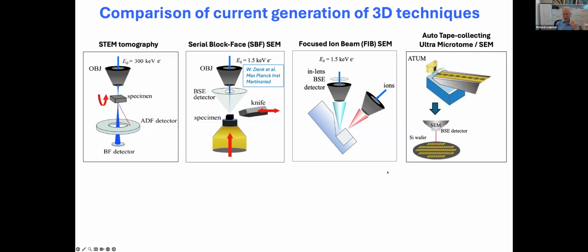And then at Harvard, there's this ATUM technique, which is technically challenging, to be able to cut serial sections, essentially, and put them onto a tape, which goes right into a microtome, and that tape collects literally thousands and thousands of sections, all lined up, and then they get deposited onto a silicon wafer. That silicon wafer can have thousands of sections on it, and maybe 100 different wafers altogether to get an entire volume, and that is imaged in an SEM with a large field of view. One thing that this requires, which is not in this diagram, is a multi-beam SEM in order to do this, because there are just too many voxels or pixels to collect.